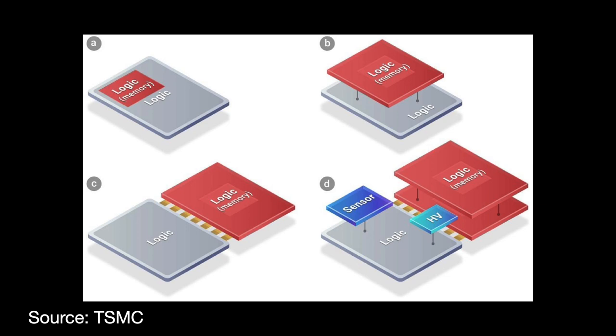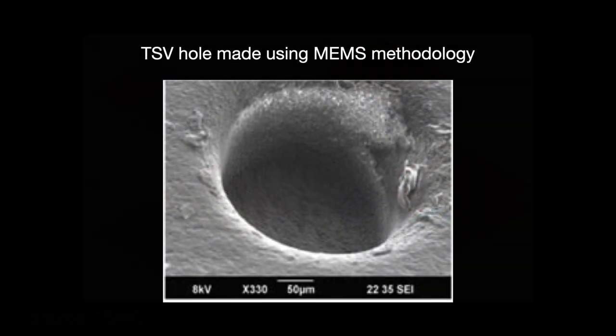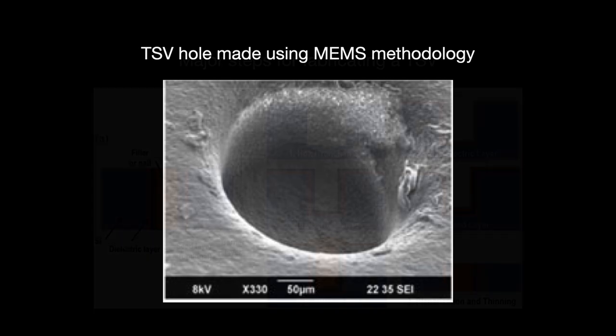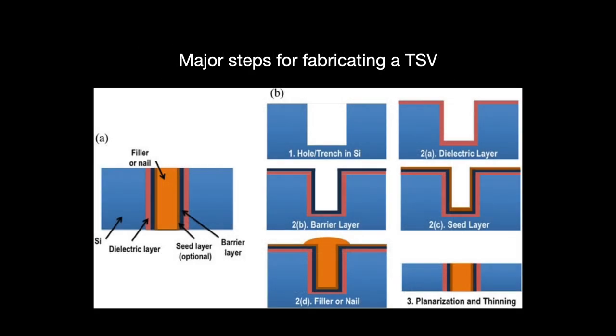There were significant manufacturing issues to overcome before 3D stacked die systems could hit the market. First, we needed TSVs, and the industry had to decide how to form them while avoiding failure modes. The TSVs are very small — about 2–10 micrometers wide and 40–200 micrometers long — and have to go through a multi-step process: etching, lining, filling, revealing, and so on.